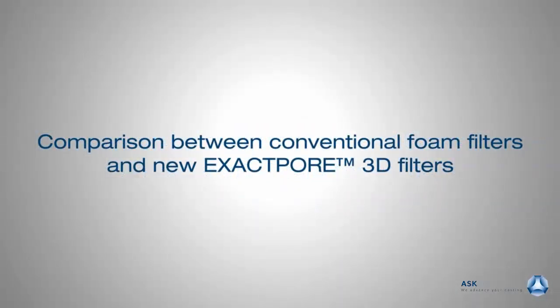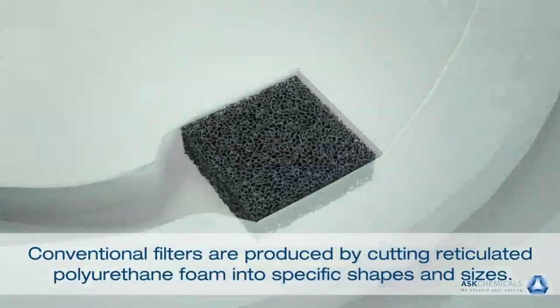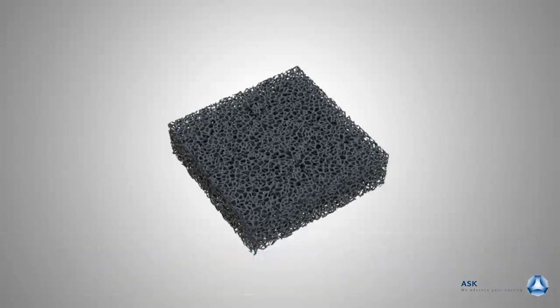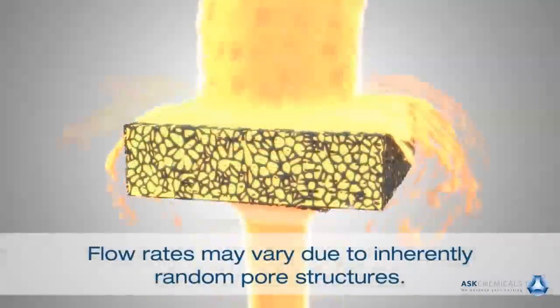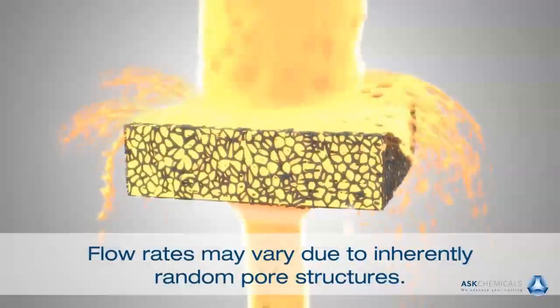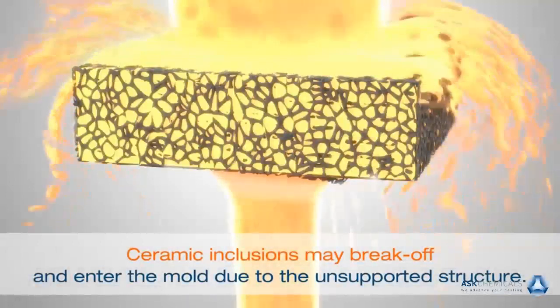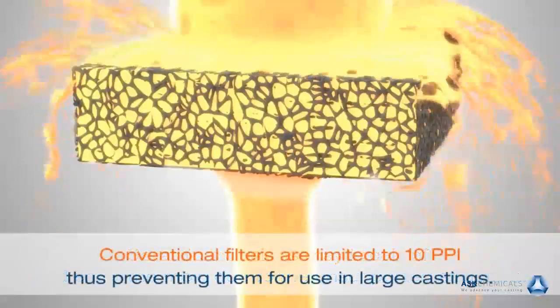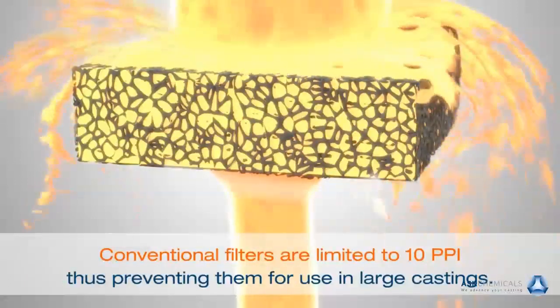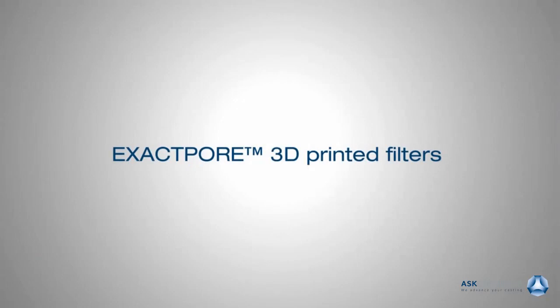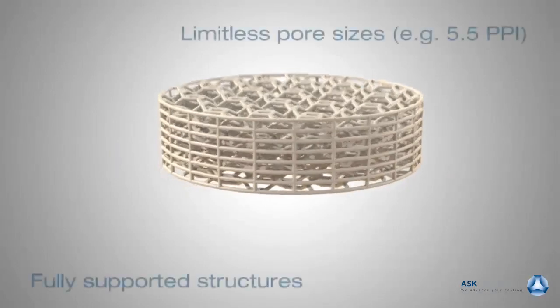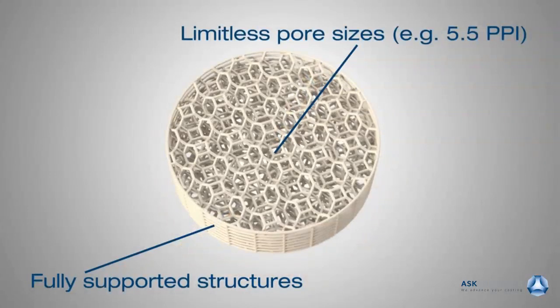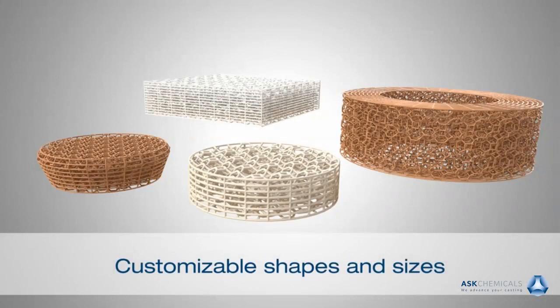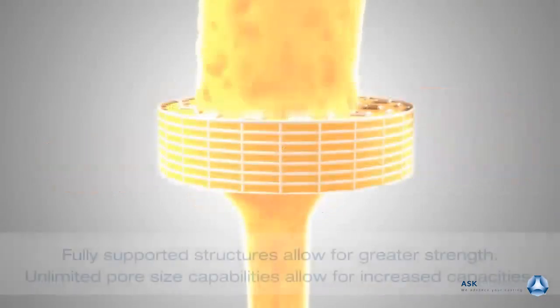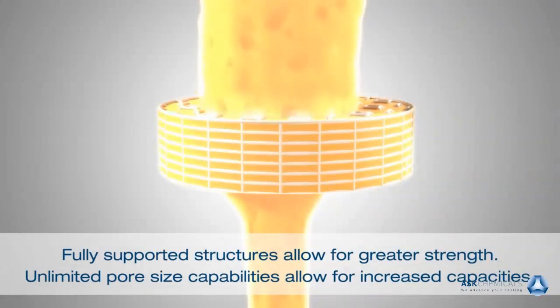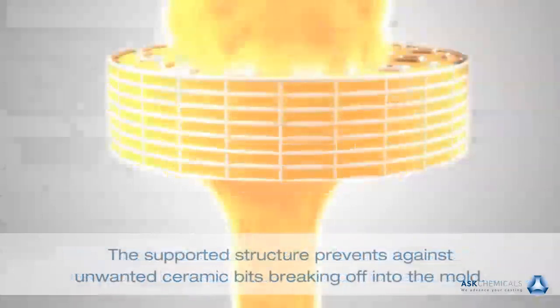When comparing foam filters to the new ASK ExactPore 3D filter, one can see inconsistency with the foam reticulate pore size. This can lead to variation in flow rate and capacity. Unsupported tendrils are fragile and can be damaged in shipment or mold insertion. This can allow filter bits into the casting cavity. The ExactPore filter was designed to fully support its filter webs with unlimited cell sizes available. These filters are also offered in many customized shapes and sizes. The fully supported structure allows for greater strength, while increased cell size improves capacity.